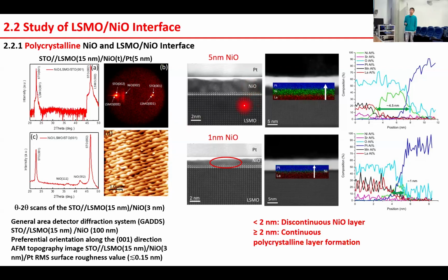We also measure the HAADF image of the cross section, and also the EDS line profile across the section, where the 5 nanometer shows a relatively flattened and continuous interface, while the 1 nanometer EDS line profile shows the platinum overlapping the nickelate, across the nickel element, indicating the element distribution from the interface, indicating the 1 nanometer nickelate is discontinuous, which is consistent with the HAADF image here.